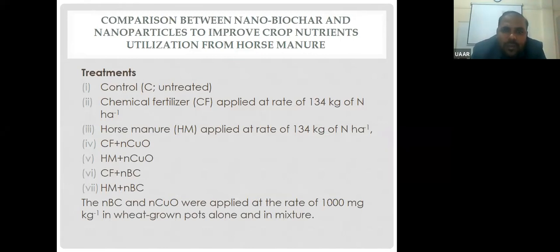In the next experiment, comparison between NANOBIOCHAR and nanoparticles to improve crop nutrient utilization from horse manure, there are 7 treatments. One was control where nothing was applied, and one was chemical fertilizer where chemical fertilizer urea was applied at the rate of 134 kilogram of nitrogen per hectare. Then horse manure was applied at the same nitrogen application rate of 134 kilogram per hectare, and then there was combination of chemical fertilizer plus copper oxide nanoparticle, which was applied at the rate of 1000 milligram per kilogram of soil, horse manure, and then copper oxide nanoparticle, and then chemical fertilizer with NANO-BIOCHAR of goat manure, and horse manure with NANO-BIOCHAR of goat manure.